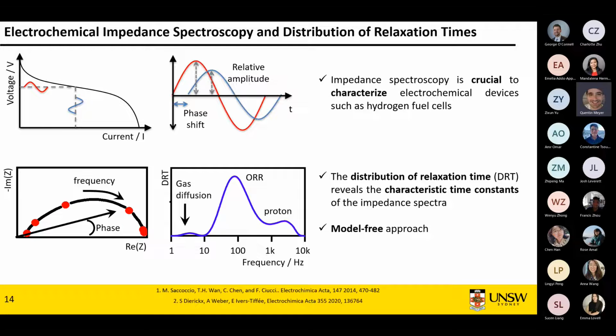So for fuel cells, the way it works is there have been a lot of groups who spent a long time doing some very nice peak identification. But overall, the best way to identify the peaks in your process is thinking of what slow process I'm looking at. In our case, we know gas diffusion is very slow, so it's going to be at very low frequency. Proton transport and electrolyte resistance in the membrane are very fast processes. That's very likely happening here. And then the reaction I'm looking at, in this case, the ORR, would be the middle peak. And this has been very well studied on fuel cells. So that's why we're quite confident in how the peak allocation works.